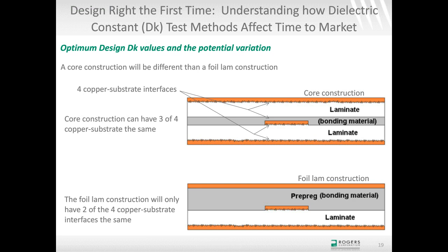So that's one issue, is a stripline circuit has different areas that can have different copper surface roughness. And then the other construction is the foil lam construction on the bottom, and that's where you just use a laminate and a bonding material only to make a three copper layer structure. And in this case, the foil lam on top is the choice of the fabricator many times, and that could be a different copper surface roughness than what is used in the laminate. And because of that, now you probably only know the copper substrate interface roughness of the laminate only, which is the two interfaces, and you have two other interfaces that are rather unknown. So that's a variable that's kind of hard to deal with for design Dk.